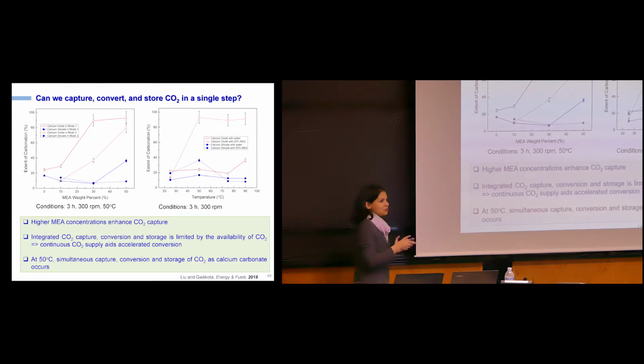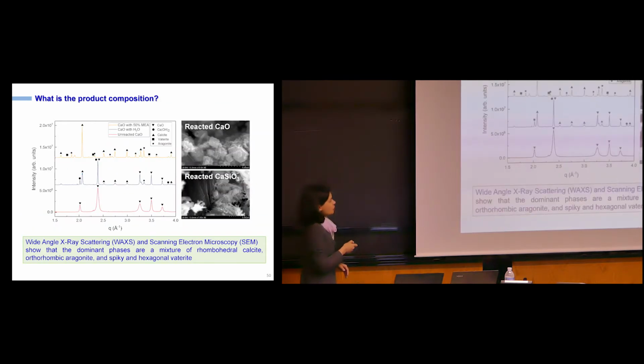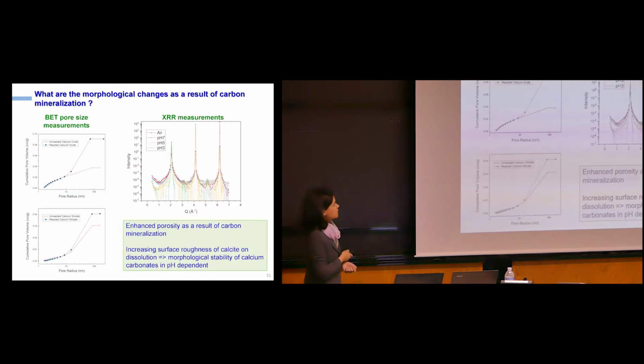Silicates are harder to carbonate, but even that is pretty good. And all of this is at much lower temperatures of 50 degrees centigrade, not 150 degrees centigrade. Again, we looked at effective temperature, and we can do all of this at 50 degrees centigrade, so this is great. Problem is that we don't understand what is the cause of the polymorphism. So I just have maybe like 2 more minutes that I'll take up of your time. So we tend to see a lot of calcium carbonate phases form, but 3 different types, 2 metastable phases and 1 stable phase. So the 2 metastable phases are vaterite and aragonite, and the stable phase is calcite. Now we are trying to establish the surface science basis for why we expect to see this polymorphism occurring.